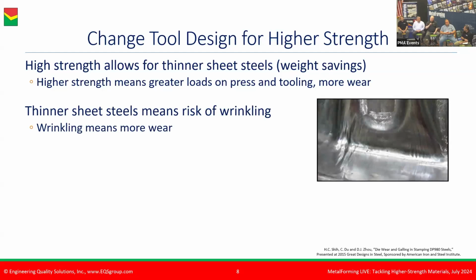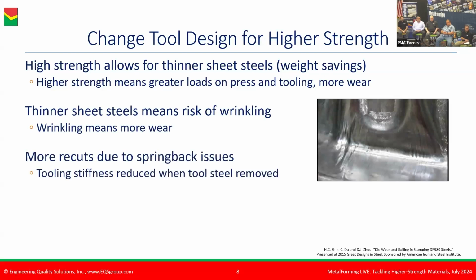But because we're dealing with thinner metals that are now higher in strength, we have a greater risk of tooling wear because these products are more prone to wrinkling. Now, remember, it's prone to wrinkling because they're thinner, but also we hopefully are going to have enough tonnage to hold it back in the binder. One of the challenges with these higher strength steels is an increased degree of spring back. Certainly that's the case if you're going to switch to an aluminum product, but also just in general, higher strength steels have greater spring back than lower strength steels.